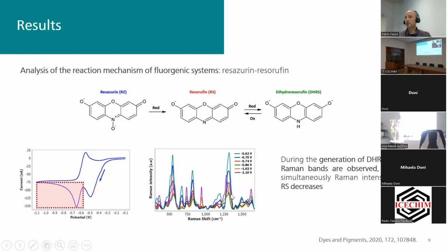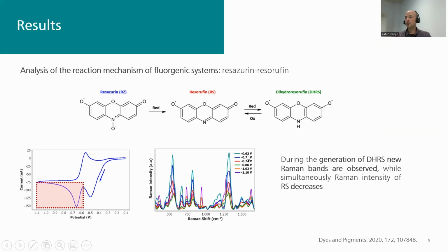And some of them, like this one, are going down during the reduction process from minus 0.6 volt to minus 1.1 volt. So this is going down with evolution. However, for instance, this one is going up during the process. So having the spectra at this specific potential and having the spectra at this specific potential, we can completely identify what is the intermediate reaction product and what's the final reaction product.